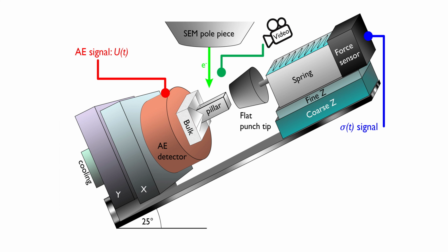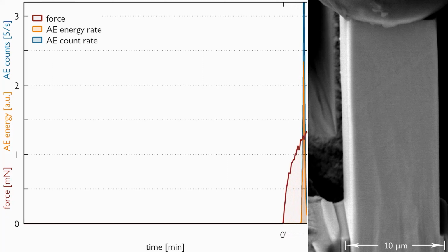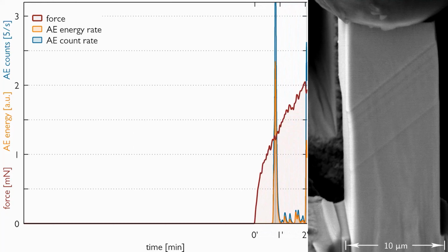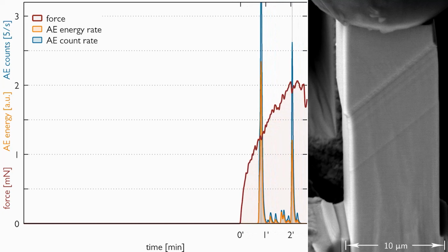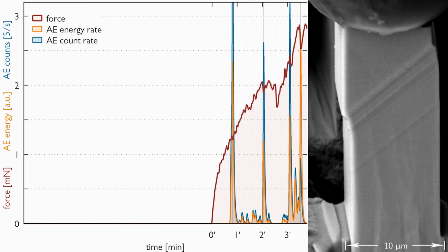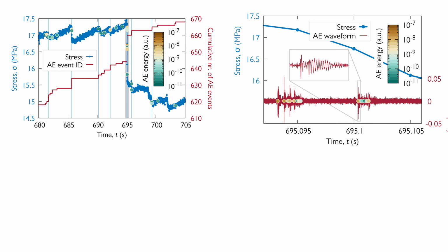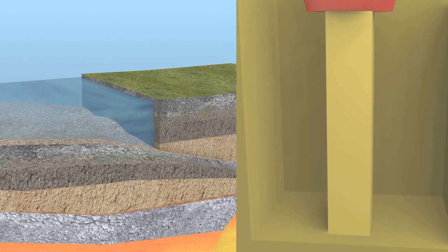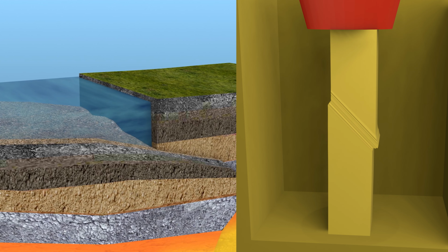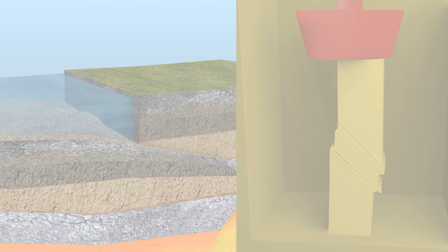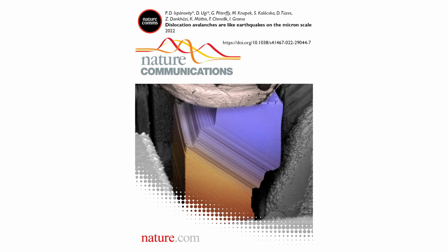We construct a unique experimental setup which can detect weak acoustic emissions of dislocation slip during the compression of micropillars. In combination with concurrent electron microscopy observations, the plastic deformation can be characterized by high spatio-temporal resolution. The acoustic emission data reveals a two-level structure of plastic events, which otherwise appear as a single stress drop. The statistical analyses show that despite fundamental differences in deformation mechanism and involved length and time scales, dislocation avalanches and earthquakes are essentially alike.